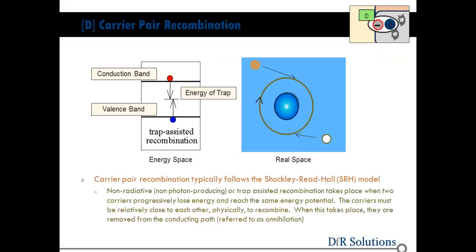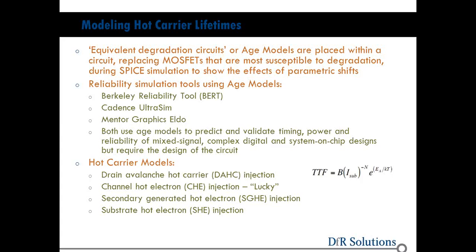One has to do with the energy space, which we've talked about a little bit of conduction and valence. The other has to do with real space. So if the electron and the hole are not near each other physically, they're not going to recombine, even if the energy exchange takes place. Okay, they'll just keep occurring. This reaction diffusion reaction model type of cyclic redundancy that's taking place. When we do modeling for hot carrier effects, this typically isn't done with a time to failure type of thing. It's more of a time to when it will affect a parameter.